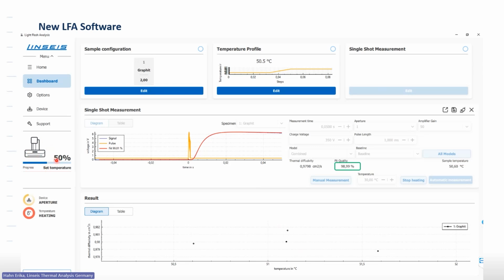We have already finished 50% of the measurement, and we can see that the system is starting to heat up to the next temperature. Here in the single shot measurement, you can see the energy or the settings of the pulse source or the laser source. In addition to that, the measurement time, aperture, and amplifier. The latter two are for the detector, but all three properties on the top are also optimized by the software.